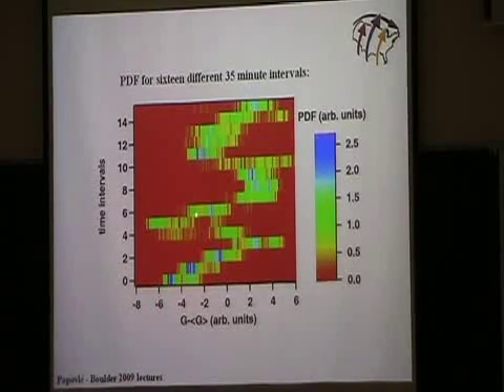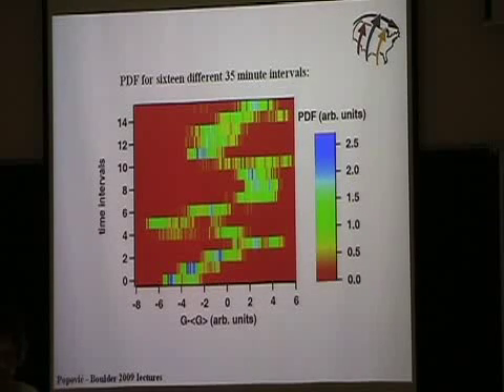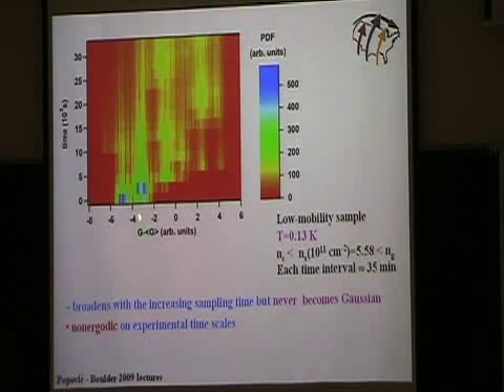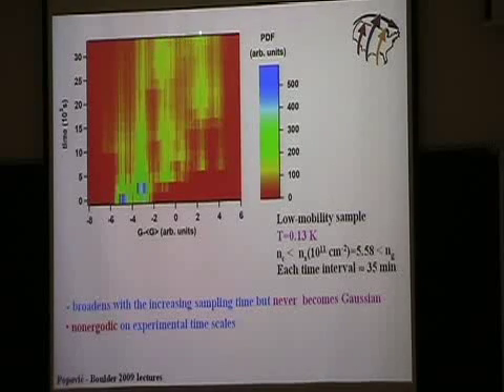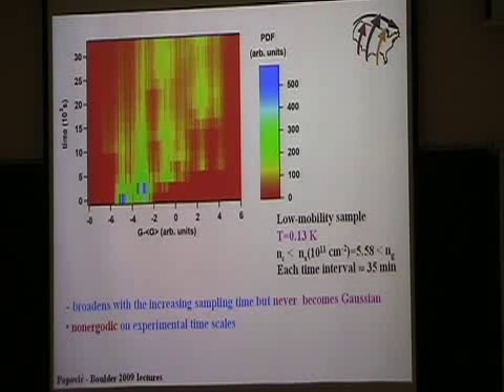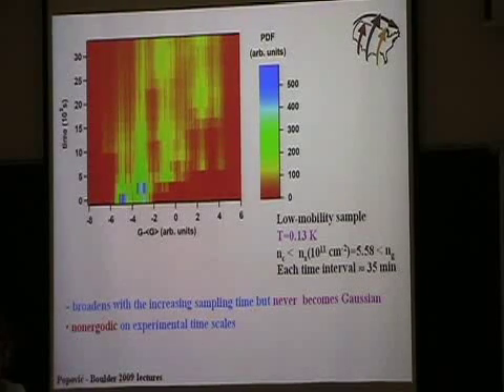So as a function of time, it wanders around. And you can say, okay, but maybe after all this time, which is about 8-9 hours, maybe you get a nice distribution, but you really do not. So this is as a function of time. So this is 0, and here we are just increasing the time. You can see even after about 8 hours, there are still like 2 big peaks and a lot of structure in between. So on experimental time scales, it never becomes Gaussian. So if you want to study PDFs, tough luck, because they don't really have a nice shape. They change all the time. So I think that's not useful in this case.